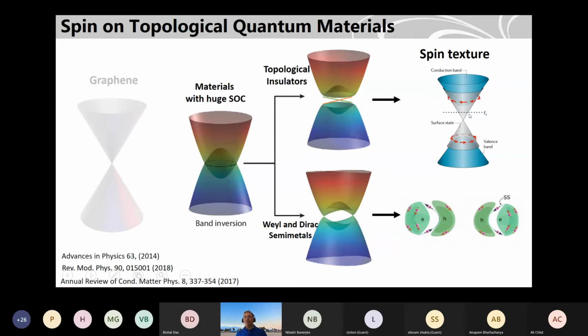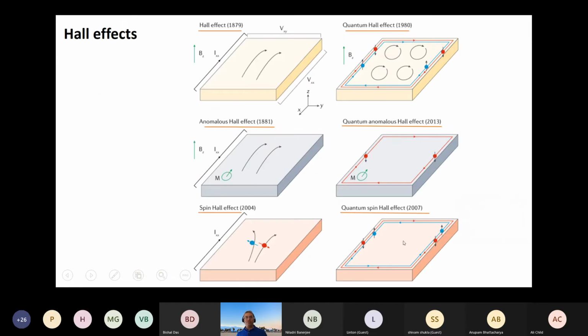So for example, the graphene-like structure here, as you see, is quite different because it's coming from the internal spin orbit coupling. So the spin and momentum are perpendicular to each other. It's called spin momentum locking. Such phenomena can give rise to a spin polarization when you apply an electric field. And also in the Weyl and Dirac semi-metals, there is an electron pocket and a hole pocket here. This is called a Weyl node. And these Weyl nodes are actually connected by a Fermi arc. This is the Fermi arc. And so many things here are spin polarized. So that will be interesting.